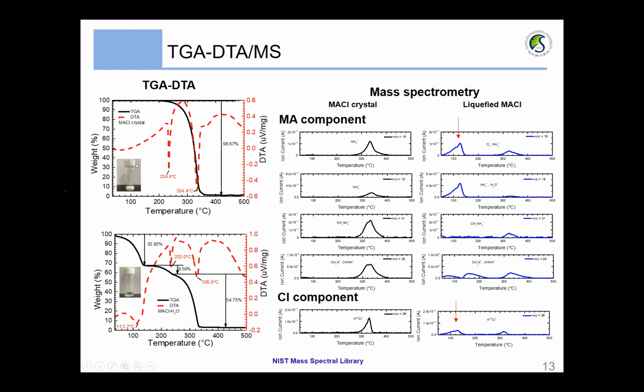We prepared two samples. Interestingly, we observed that MACl exhibits a very hygroscopic characteristic: it becomes liquefied within a day after exposure to humidity. So we continued to measure the TGA. The top one is the dry MACl sample, and the bottom is the liquefied MACl. Both samples exhibit an endothermic process, which absorbs heat for the decomposition. But there was a significant initial weight loss observed from the liquefied MACl at a lower temperature.